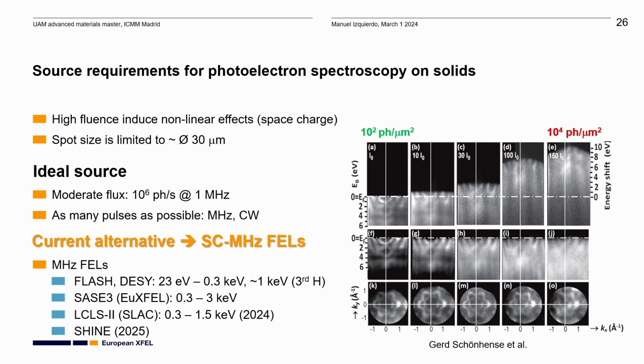So why is there a limitation? Photoemission at synchrotrons has been a very successful technique. However, at free electron lasers, there was until last year only one place in the world, which was FLASH, where this could be realized. And why is that? The reason is that photoemission is pretty much affected by something called the space charge effect. This is very easy to understand and has been measured experimentally.